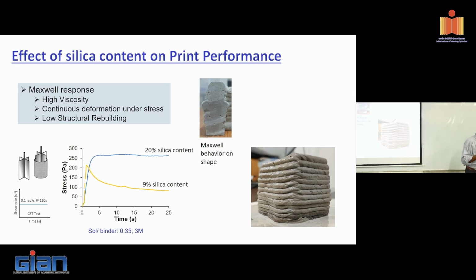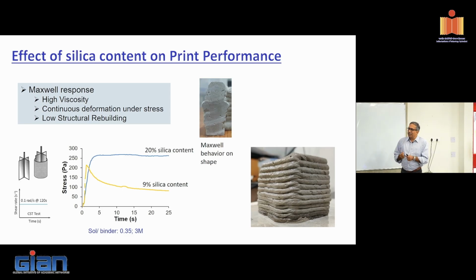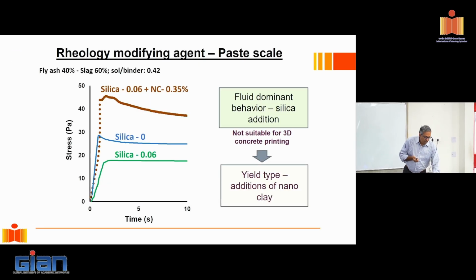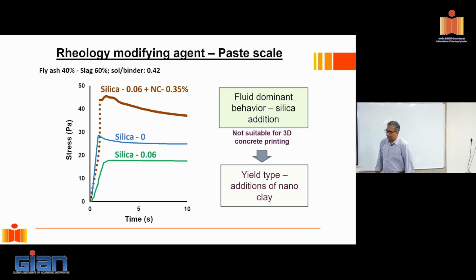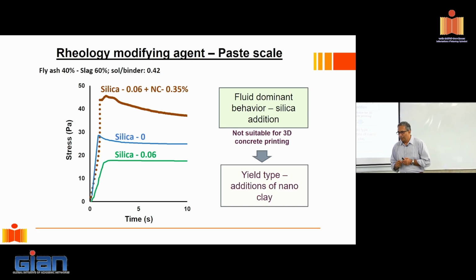So remember the levers that we had when we were doing the concrete mix design? We had the basic things that I could control, right? But then we had these admixtures. That was my final lever, right? Can I put something in there that will help me with structuration? Well, what we found is that if we start adding clay in the material, okay, so what are we doing with clay? We are basically relying on the clay to give me the structure.